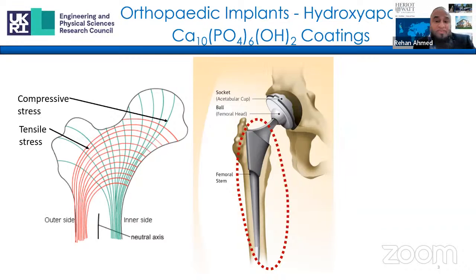So the through thickness residual stress profile in these coatings changes during the life of the implant. It's like a living thing, you can say, and it changes due to the mechanical loading. It changes due to the interaction with the biological environment in the body, and any post-treatment which has been applied to the coating. And in the example shown for the hip implant here, the femoral stem is coated with hydroxyapatite coating, and the implant is subjected to a compressive stress and a tensile stress throughout its life, which can lead to failure amongst other factors such as the biointegration.